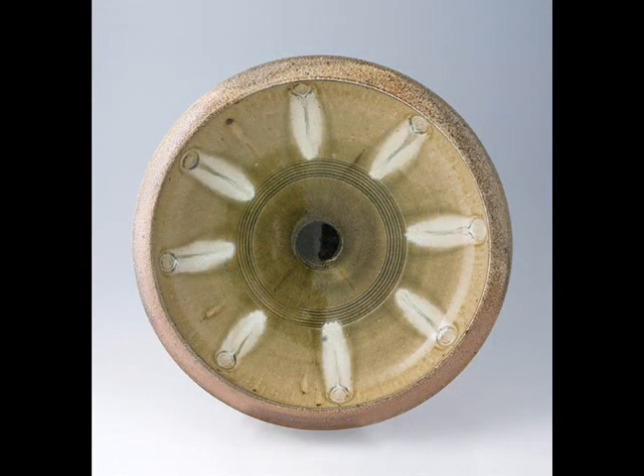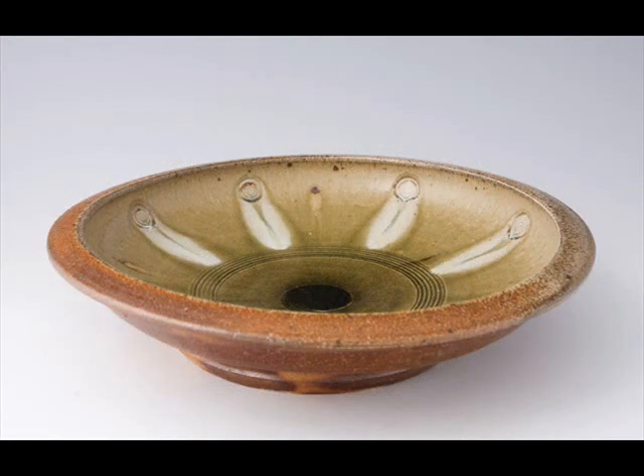PR 1205, a charger. I really love to make these large plates. I make them from 35 to 40 pounds of clay, and they only just fit in between the props on a kiln shelf. The glaze inside is my pine ash glaze, and over each of the stamped roundels I've laid down some nuka glaze, which moves down the side of the pot during the firing.